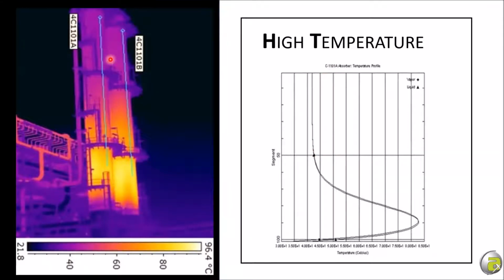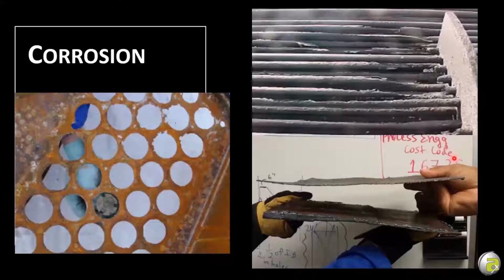And then we went out and took the thermal imaging camera, and you can see that the simulation matched what the thermal imaging camera showed. Nice cool 40, 43 degree top part of the tower, lots of final absorption, easy to meet spec, all the reaction at the bottom of the tower and at temperatures less than 85 degrees. So if you have a simulator, you can predict trouble, and you can use a thermal imaging camera to make sure that you're actually seeing it. These are all tools that you can use to improve performance at high temperature. So that's it for meeting spec.